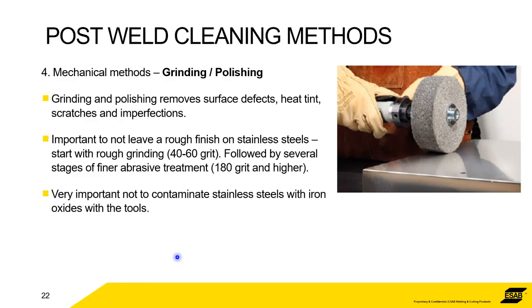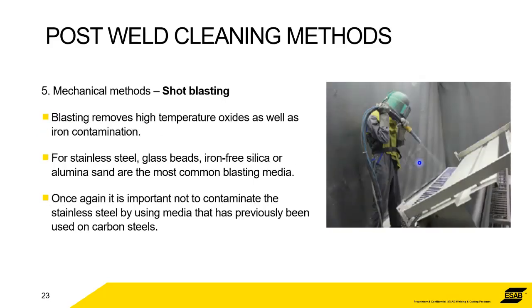Makes a big difference. And obviously, we say it again, it's very important that you mustn't contaminate the tools that you've been using on carbon steel. You mustn't use them on stainless steel afterwards. All you will do is embed iron into the surface of the stainless, so it'll completely get rid of this chromium oxide layer. Again, I keep going on about the chromium oxide layer, but that's what's important.